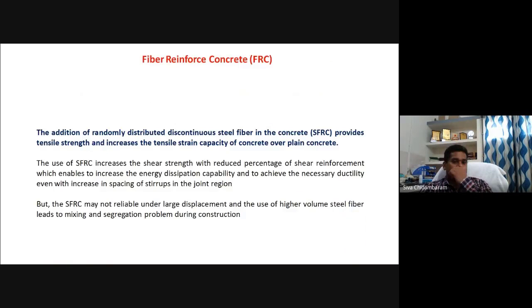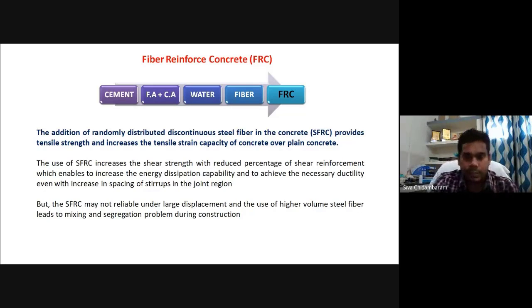In conventional fiber concrete, if you add a fiber, that is called fiber reinforced concrete. Conventional concrete can take a certain amount of fiber, not more than 2% of steel fiber. If you are using synthetic fiber, not more than 0.5%, as that will create a lot of workability issues. When you add fiber, the concrete cracks get arrested, and generally the crack will not grow very rapidly because of the presence of fiber. The fiber will bridge the cracks and not allow them to grow rapidly.